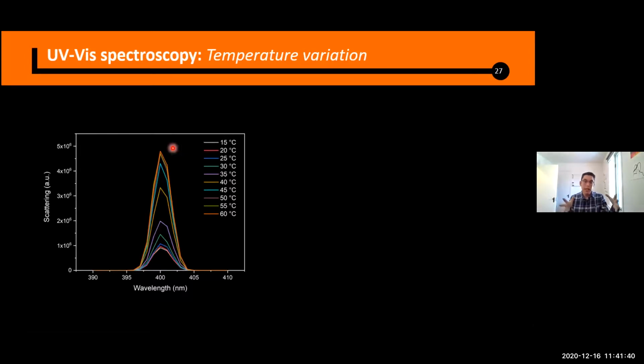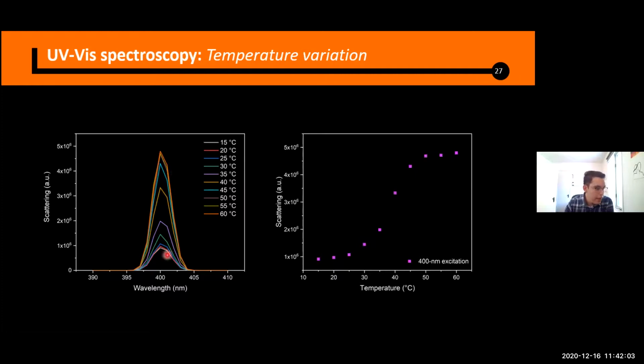And this is mainly because even if the particles are smaller, the hydrogel network is more dense. So in this case, this more dense sphere will scatter more light as compared to the swollen state, where because of the network, some light can be absorbed. And if we take the peak of the scattered light as a function of the temperature, we obtain a similar curve as I showed you before with the hydrodynamic diameter as a function of the temperature. And here we can see that the critical temperature is about 35 Celsius degrees, which is very consistent with what I showed you before.